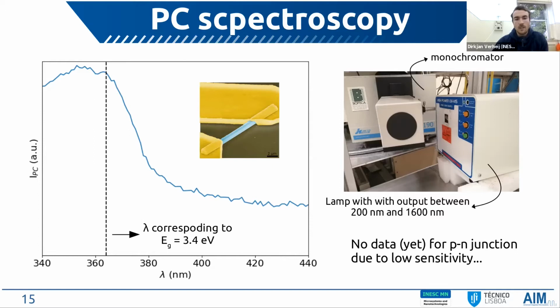And this actually has a consequence that, for example, with the n-type microwires, we can do photocurrent spectroscopy measurements, in which the light is divided into individual wavelengths using a monochromator, which we cannot do yet for the PN junction due to this low responsivity. Because of the division of the light into individual wavelengths, the intensity is much lower. And when illuminating the PN junction, we actually cannot read an electrical signal, and consequently, we are not able to perform this measurement. Now, talking a little bit about the measurement itself, as you can see here, when approaching the wavelength corresponding to the band gap of gallium nitride, we see that the photocurrent starts to increase, and this really shows that it is gallium nitride we are measuring and not something else.